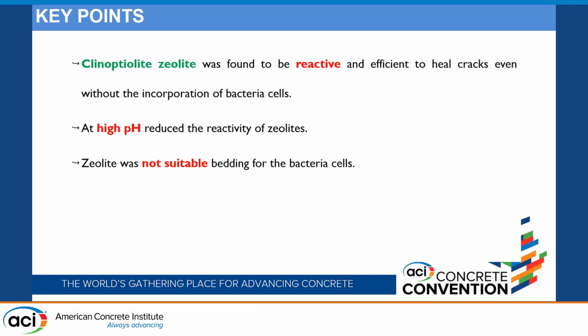When we look at the clinoptilolite zeolite, we can easily say that zeolite was not a suitable bedding for bacteria cells. This was attributed to the limited pore size of zeolite. Therefore, most of the bacteria cells were adsorbed on the surface of the zeolite. If the bacteria cells were not embedded in the natural mineral, they might be more prone to the negative impacts of the high alkaline conditions of the cement base. But on the other hand, we can say that clinoptilolite zeolite was found to be reactive and efficient to heal the cracks without incorporation of the bacteria cells. And moreover, its high pH reduced the reactivity of the zeolites.